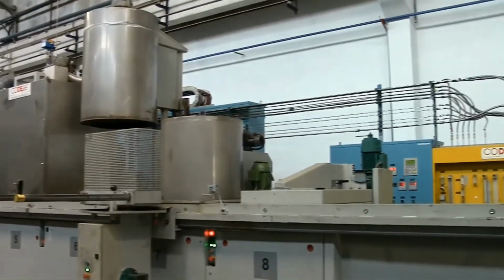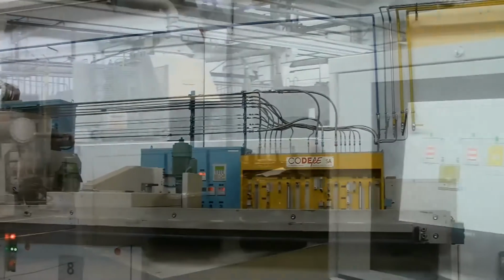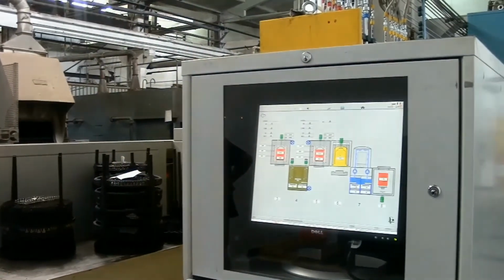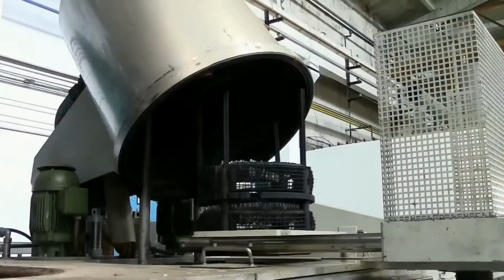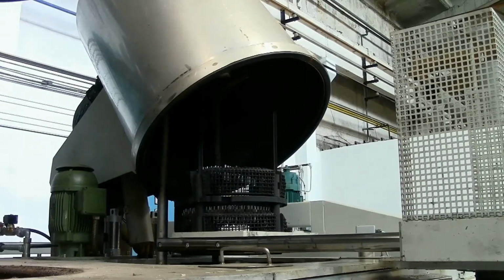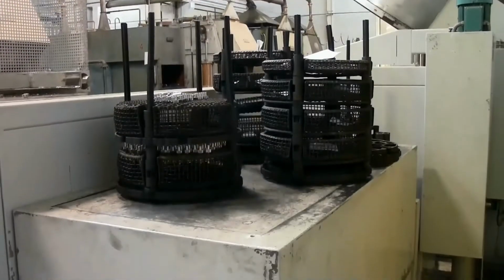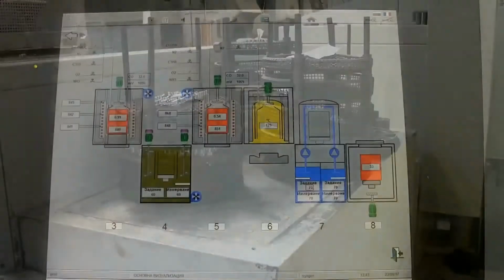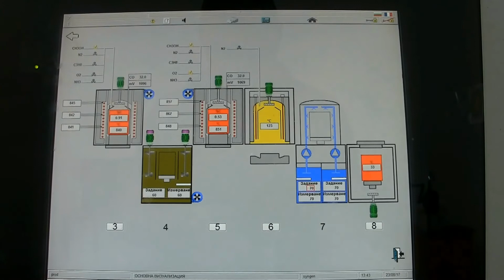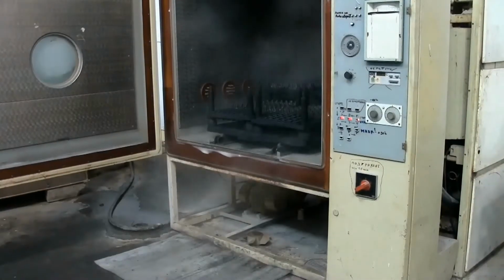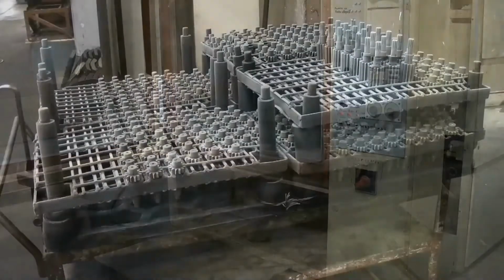The heat treatment of gear wheels of modules 0.75 and 1 mm is made on a newly bought technological line purchased from company Codier. This up-to-date modern jewel allows us to get a cement layer scattering within 0.2 mm and the measured hardness of the loaded parts within 1 unit of Rockwell.